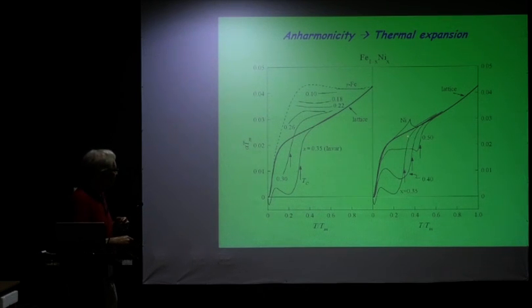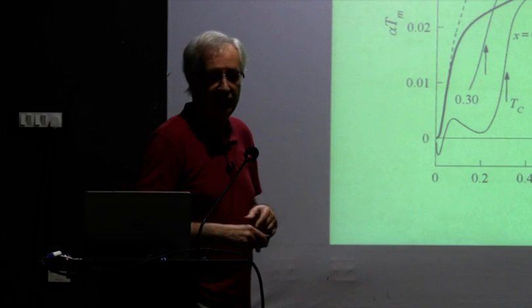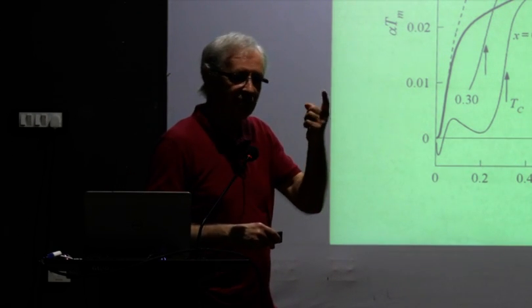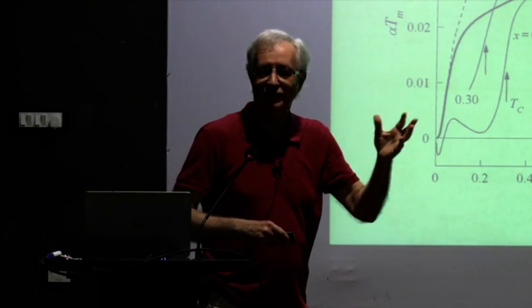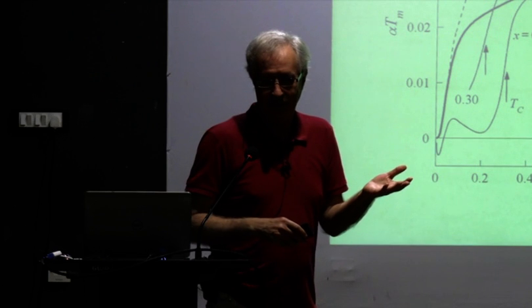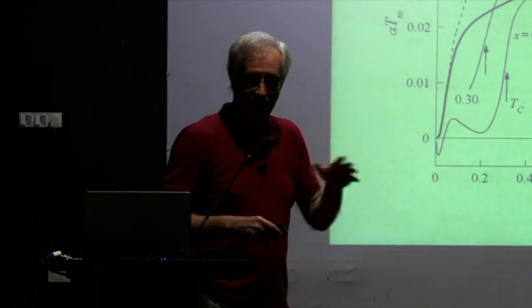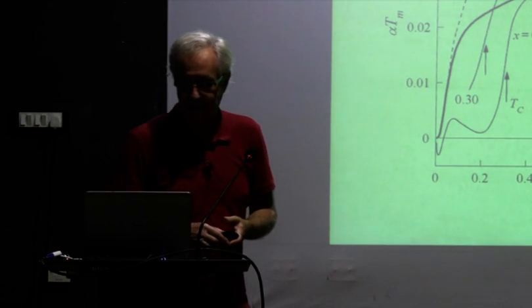When we look in this panel, this is just a continuation. We didn't plot everything here because then it gets too complex. We have this repeated here, the 35, same curve. And then as you add more, this time it starts coming from below and merges with the curve of nickel, which conforms to the general lattice expansion property above a certain composition of about 70% or something like that. And interestingly, that 70% is the composition which everybody talks about these days in thin films and this and that of permalloy. Okay? So these are all quite interesting coincidences.